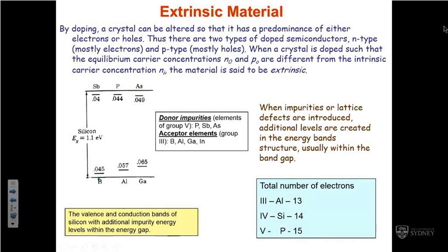And again, here boron is also, these are very good values for acceptors, very small. This value represents the energy from here, valence band maximum, up to there. So 0.065 from here, energy 0, up to there, so that electrons can easily be excited from here up into there, leaving behind a hole. Up here we have, remember our donors, antimony and phosphorus. You can see the 0.04 corresponds to the energy from the conduction band minimum down to this eigenstate here. So this is very close to the conduction band minimum. So that's a very efficient kind of electron donor.